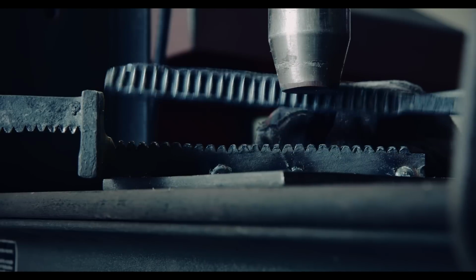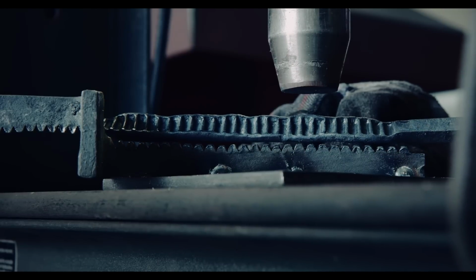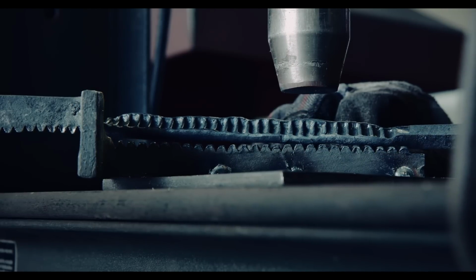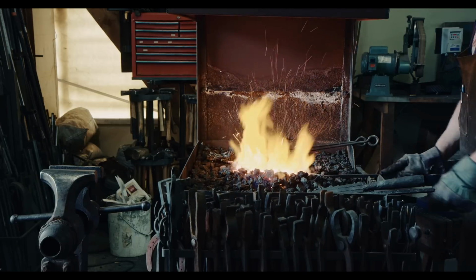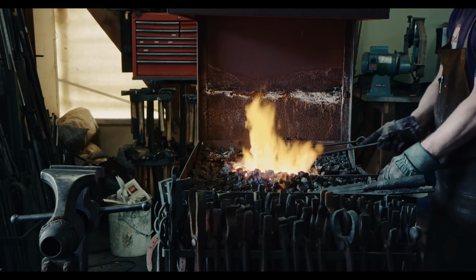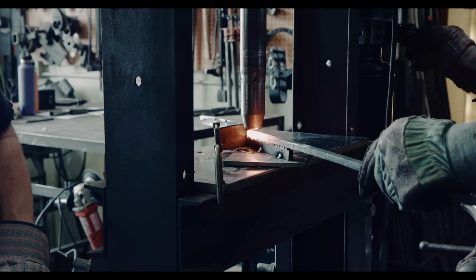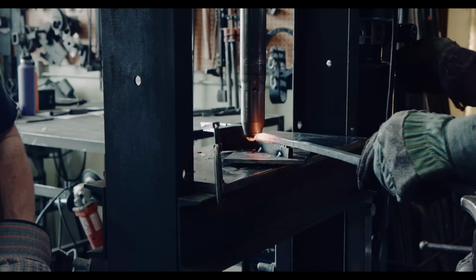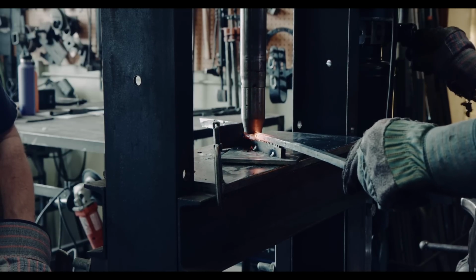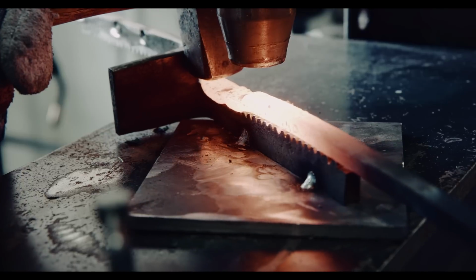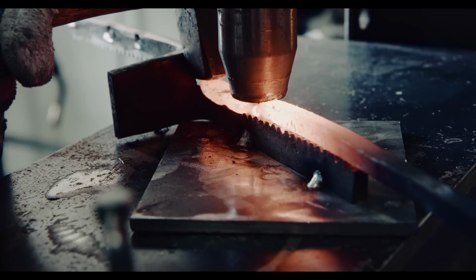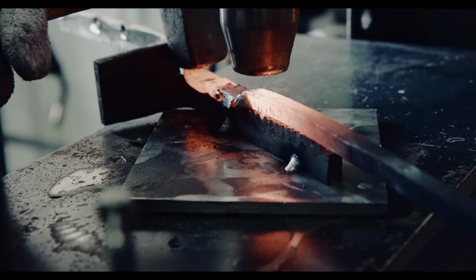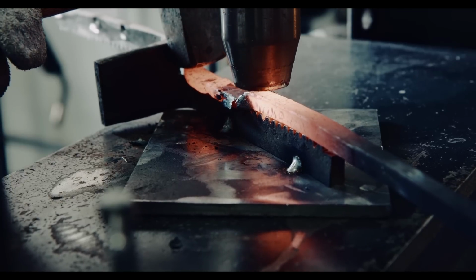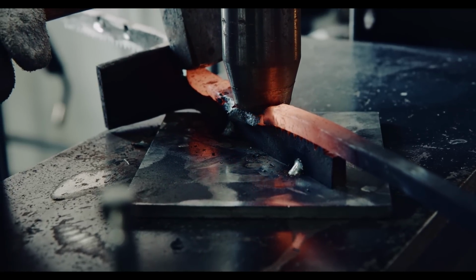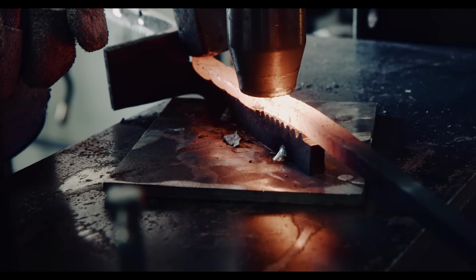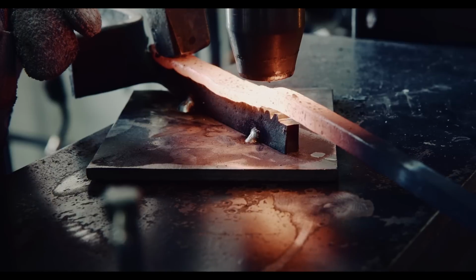Here is how it looks like after the wrought iron has been formed. Once the wrought iron is hot, I have enough time to press 2 to 3 times before the heat is lost and I need to go back to the forge. Alignment is important here, and you may notice that the bar is bending away at the end. I somewhat corrected for that, and fortunately there is enough material so that it should not become a problem.